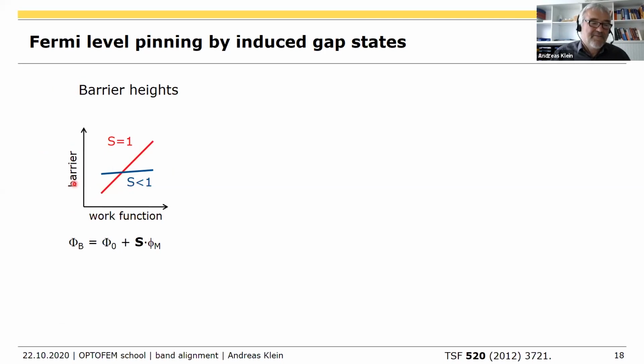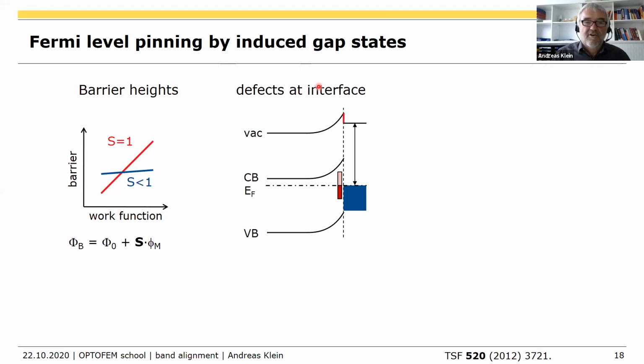As I emphasized, the Schottky barrier height is the Fermi level position at the interface. If the barrier height does not change in dependence on the work function of the metal, that means the Fermi level is more or less always at the same energy. That's why a low slope is called Fermi level pinning. This Fermi level pinning is caused by defect states at the interface, interfacial defects. We will later see that this does not need crystallographic defects at all. It's an intrinsic nature of interfaces between semiconductors and metals that you get some induced gap states. These induced gap states can be charged and they form an interface dipole.